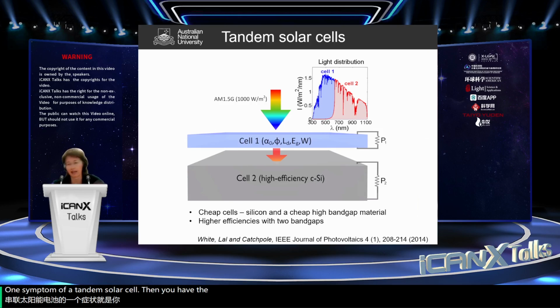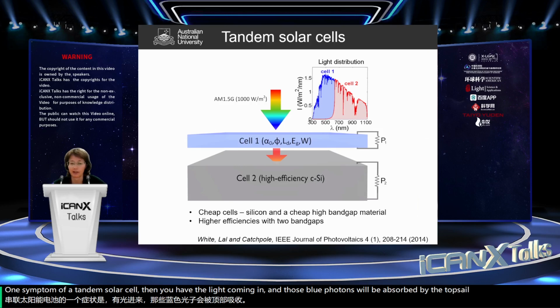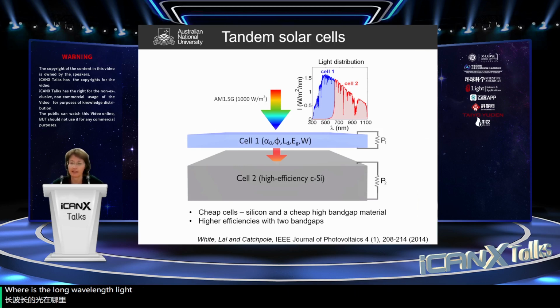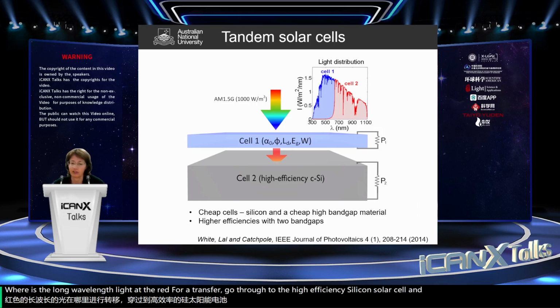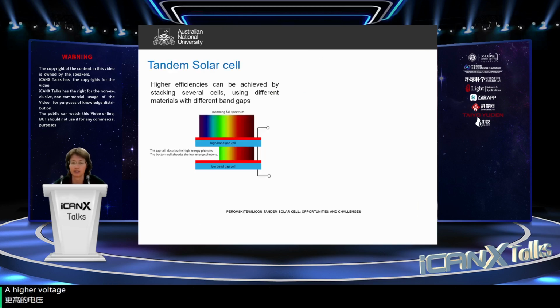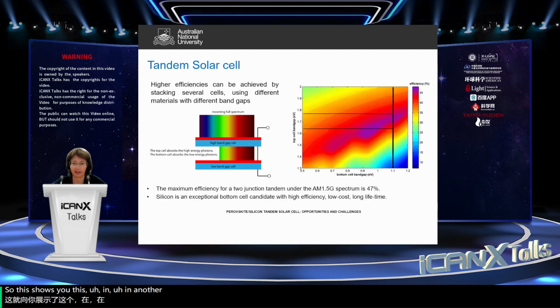Then you have the light coming in, and those blue photons will be absorbed by the top cell, whereas the long wavelength light, the red photons, will go through to the high efficiency silicon solar cell. And overall, this way you can increase the efficiency through a higher voltage. So this shows you this in another way. And if you plot the theoretical efficiency, you can see that you can get to some very high efficiencies. The maximum efficiency for a 2-junction tandem, so 2 cells, is 47%.